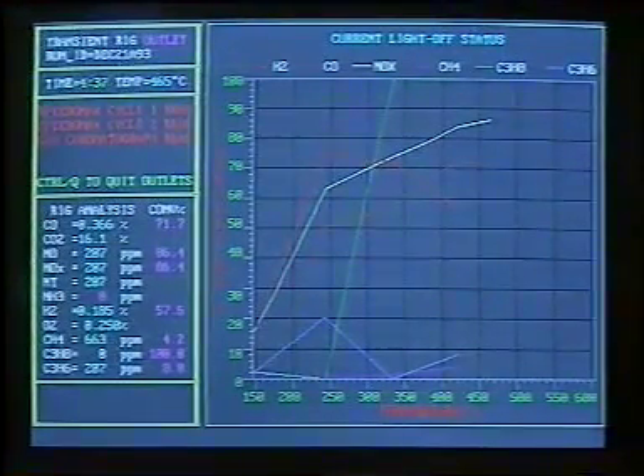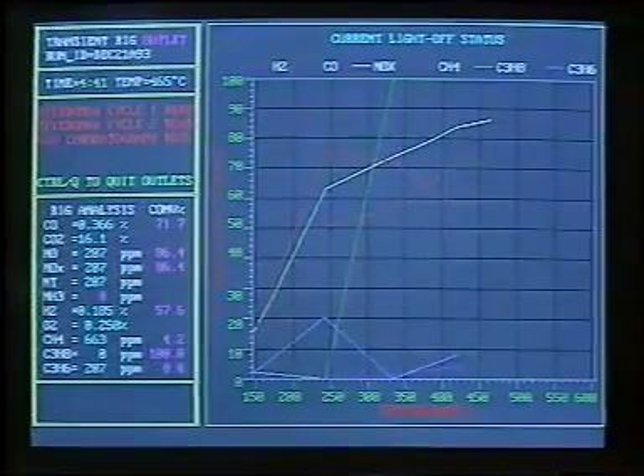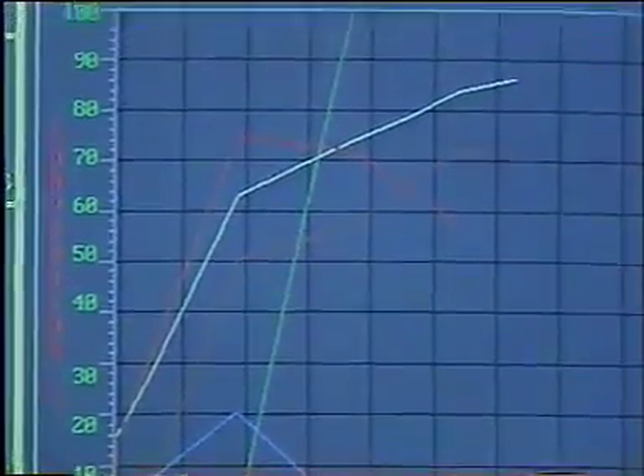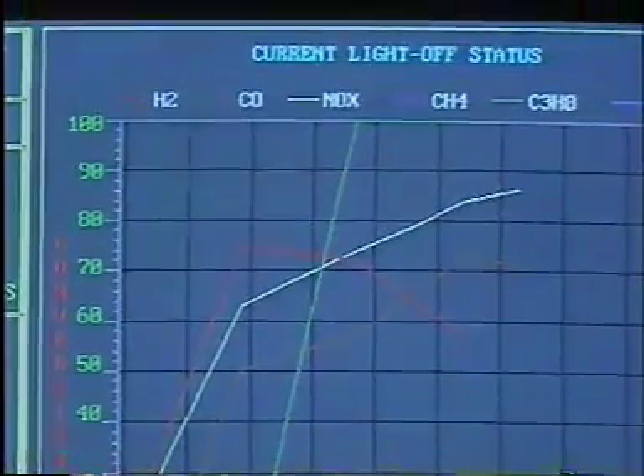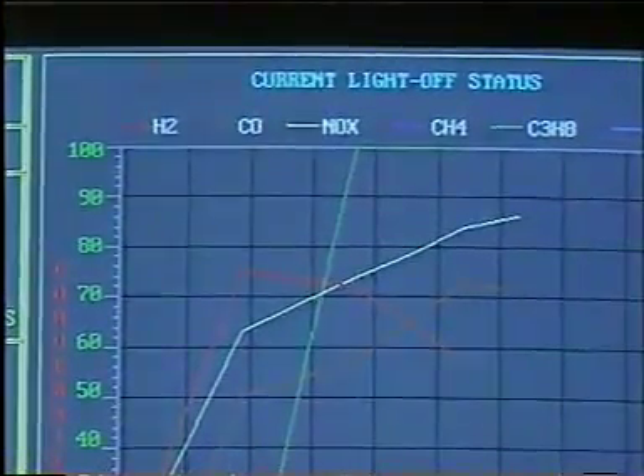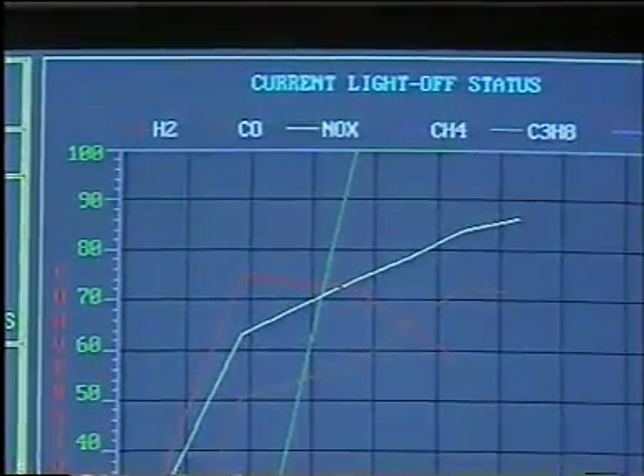The computer screen shows how the conversion efficiency for each gas varies with temperature, and you can see that below a certain temperature the efficiency is 0. This is the light-off temperature. Below this temperature, about 300 degrees Celsius, the catalytic converter performs no useful function, but above the temperature it works extremely well.